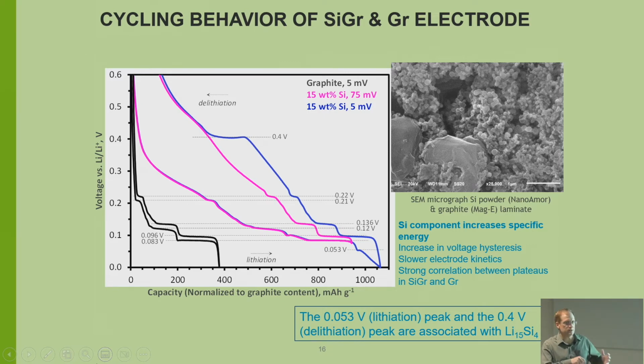But unfortunately, silicon expands greatly when you put lithium into it. Another problem: here I made electrodes that are 15% silicon, the rest graphite. And you see, as I'm discharging, I have a higher potential, which on the negative you think of in the reverse way, so that's not a good thing. We want to be down low, close to these lithium potentials. But the problem is when I discharge, I have this big hysteresis. You like to have the charge and discharge as close as possible, because that's what gives you your energy efficiency. So that's some of the work that we're doing in silicon, trying to get rid of that hysteresis.